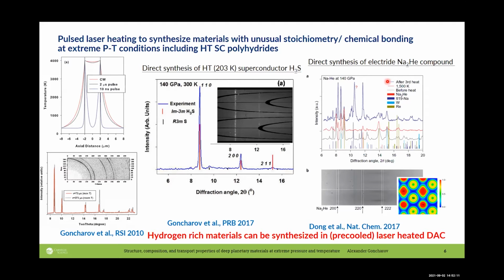I mean, you understand that helium is not very likely to form compounds. And what we did, we made the first materials with electrides. Electrides have pairs of electrons which are localized in the lattice space similar to atoms. So we synthesized these materials again at 150 GPa and several thousand degrees. So I think this is very important, and these kinds of experiments nowadays are being used a lot in the material science community, for example, for synthesis of new superhydrides.